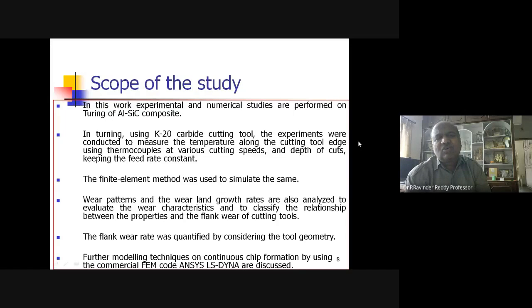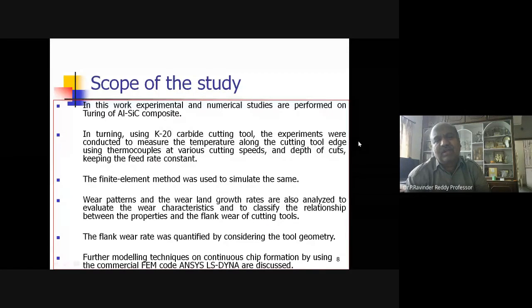The scope of the study. In this work, experimental and numerical studies are performed on turning of aluminum silicon carbide composite. In turning using a K20 carbide cutting tool, the experiments were conducted to measure the temperature along the cutting tool edge using thermocouples at various cutting speeds and depths of cut, keeping the feed rate constant. So of the three parameters, one is kept constant and the others are varied. Then finite element simulations were carried out.